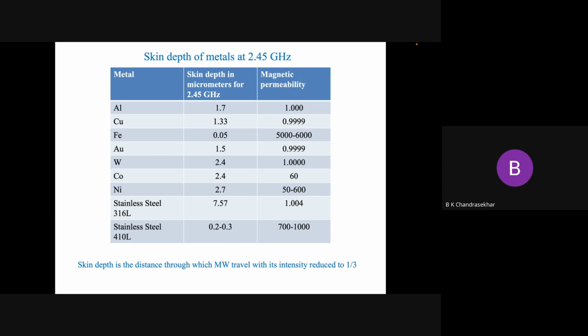and therefore when microwave radiation is incident on that, the magnetic field of the microwave interacts with the magnetic field of the stainless material, it absorbs very quickly and gets converted to heat, and therefore the penetration depth is less than a fraction of a micron. Okay, it's only 0.2 to 0.3. Whereas stainless steel 316, which is not magnetic, has got a skin depth of 7.57, which is a fairly thick layer where the microwave can penetrate inside that particular type of stainless steel. Okay, and people have studied the behavior of these type of materials, and they have come to certain conclusions as follows.